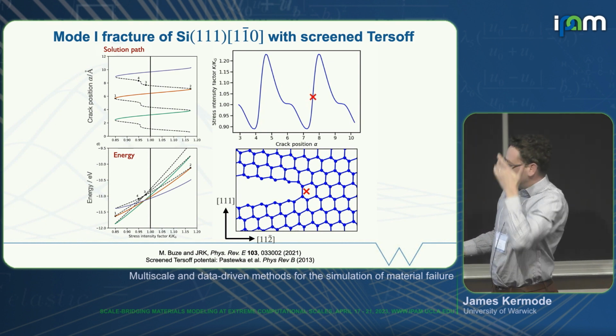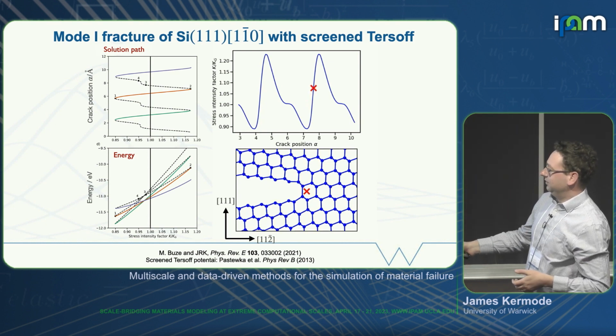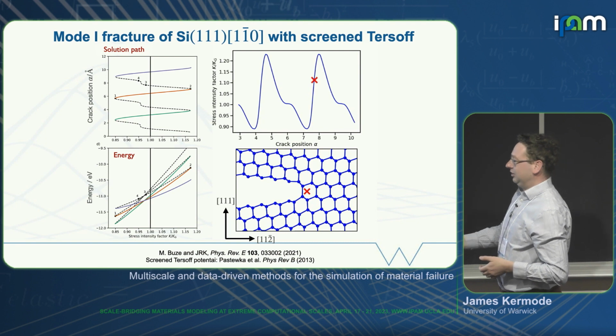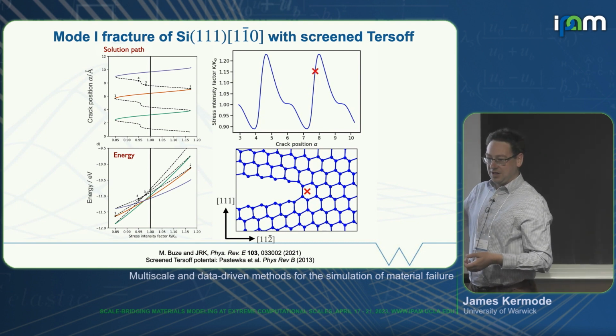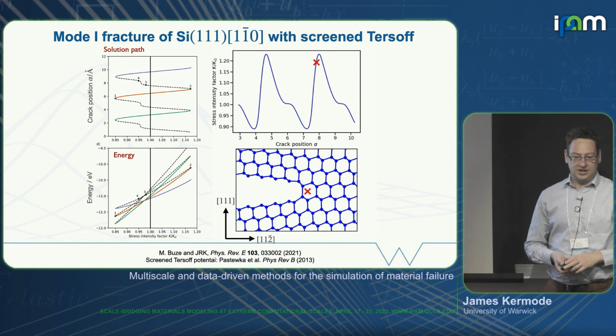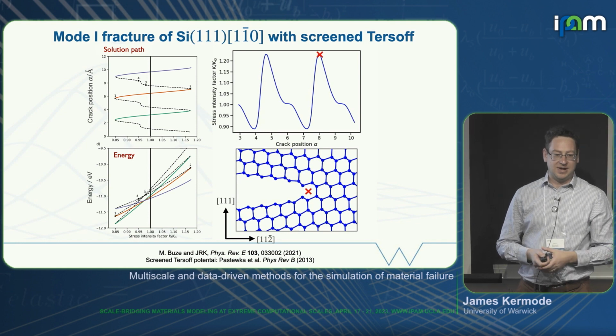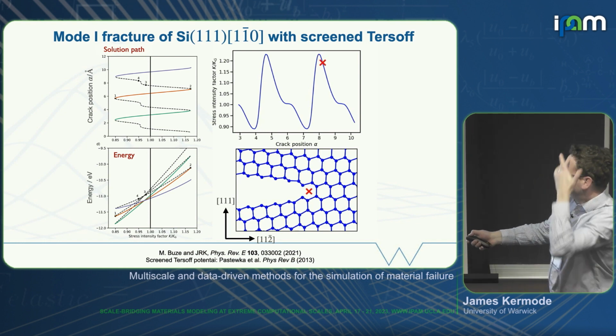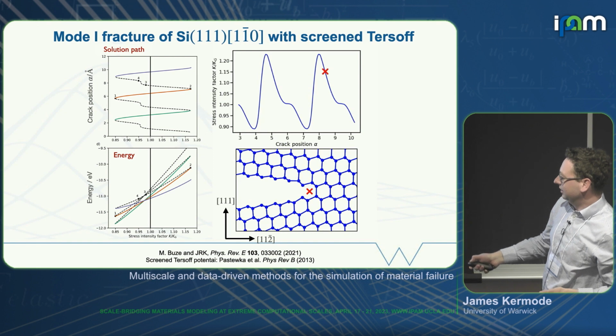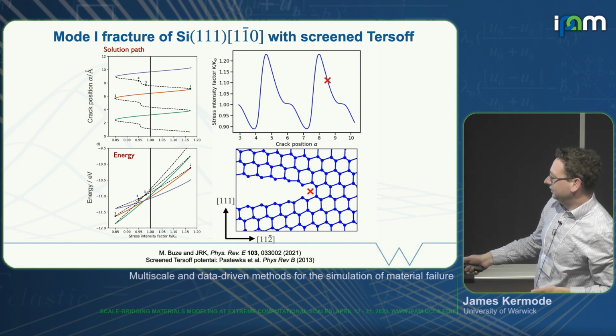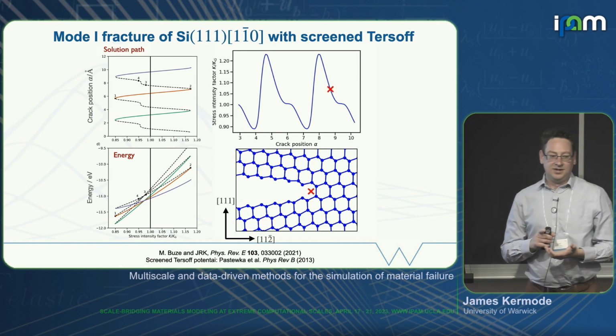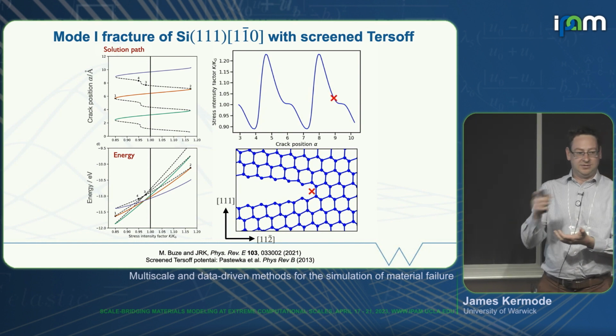The final thing to tell you about on this slide is the energy landscape associated with this set of solution paths. We do one long calculation and map out the whole thing, and then we can read off all of the energetics and all of the energy barriers from that calculation. If we take these solution paths and compute their energies, we find they all cross at a load where it's neither favorable to advance nor to retreat.